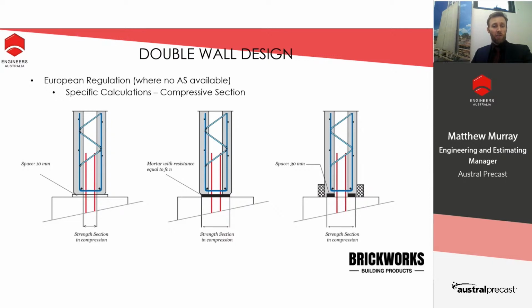So traditional precast in Australia uses solid wall precast with a mortar bed. On the left-hand side here, we can see a double wall with no mortar bed and only using a 10 mil spacer. When the concrete is core filled into the panel, if we have a space of less than 1.5 times the diameter of the aggregate size, then the concrete will not be able to fill that gap. So here, if we had a 10 mil aggregate for our first picture on the left, and only a 10 mil space at the base of our panel, the compressive section that we can only use reliably as far as an engineering calculation would go would be the core of the panel. So if this was, say, a 250 mil panel with 70 mil shells, that would only be 110 mil thick, which may or may not work for the structure.